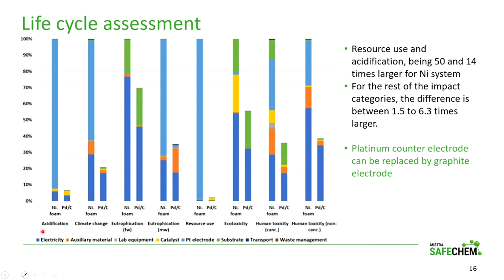Well, I can go here, but better. We look into acidification, climate change, eutrophication in freshwater, eutrophication in marine water, resource use, ecotoxicity, and human toxicity, cancer and non-cancer. And what we can see from this graph in short is that the nickel has major concerns than the palladium system. And this is particularly the case in the resource use and acidification, being 50 and 14 times larger for the nickel system. For the rest of the impact categories, the difference is not so large.